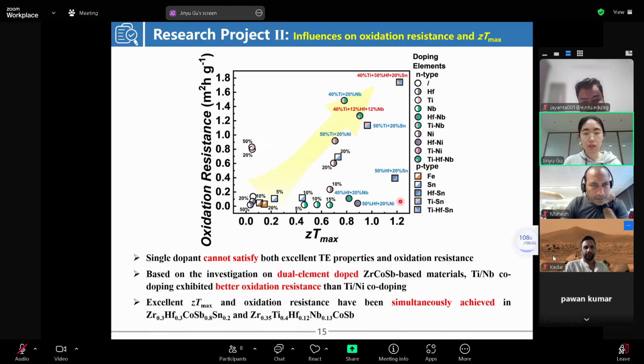I study the influences of the different dopants on the materials' oxidation behavior, oxidation rate and oxidation resistance. This figure describes the results of my study. The high concentration of titanium doping in the zirconium cobalt antimony materials will avoid the rapid oxidation of the material, and the oxidation resistance is high.